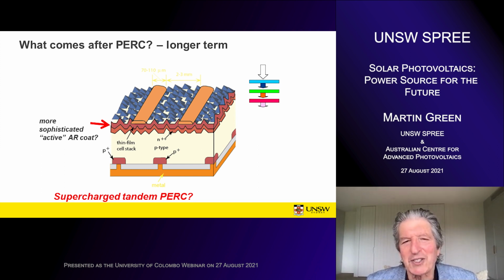But the voltage, as I said, is determined by the band gap, which is around about 1 electron volt. So you're stuck with voltages that are less than 1 volt. The energy gap is 1 electron volt, and the maximum voltage you can get out of a cell is less than that value expressed in volts, so 1 volt. But if you stack a cell with a higher band gap on top of silicon, it can respond to the higher energy photons in the sunlight. So if you stack a cell with 1.5 electron volt band gap on top of a silicon cell with just over 1 electron volt band gap, you can get a voltage that's higher, say 50% higher than silicon, from that cell that's stacked on top.